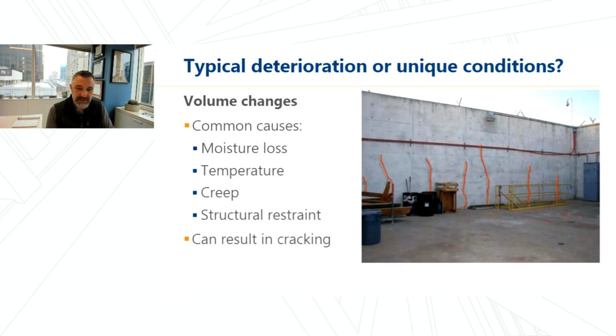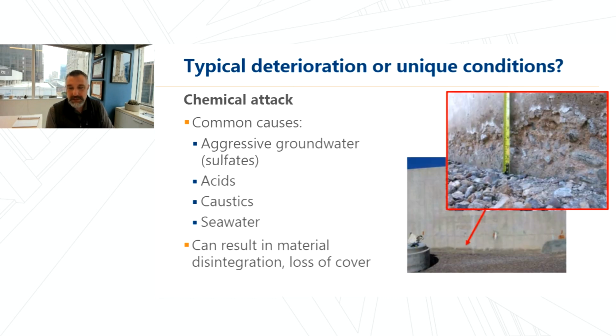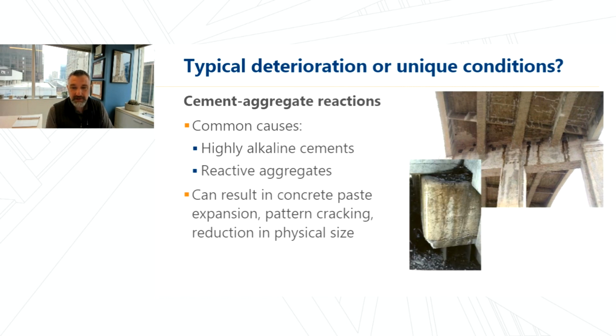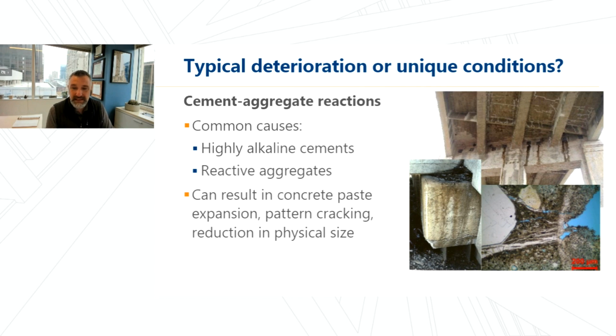So volume change, for example, is one mechanism which can be caused by several factors, and this can result in cracking, unwanted cracking. Chemical attack, which can be caused by various exposure conditions, can result in disintegration of concrete and eventual loss of concrete reinforcing cover. Cement aggregate reactions are reactions that occur within the concrete constituents, and this can result in paste expansion, pattern cracking, and reduction of the size of a concrete member, and that can directly impact its ability to withstand loads.